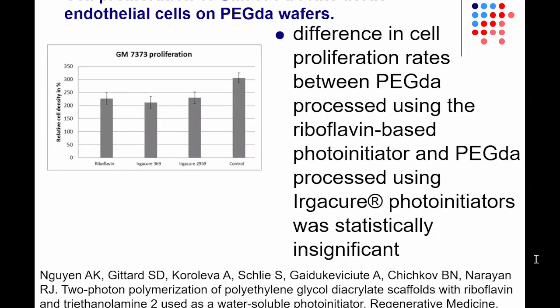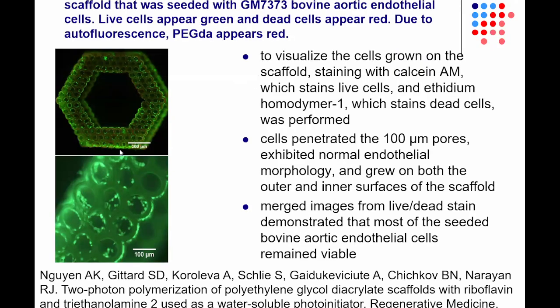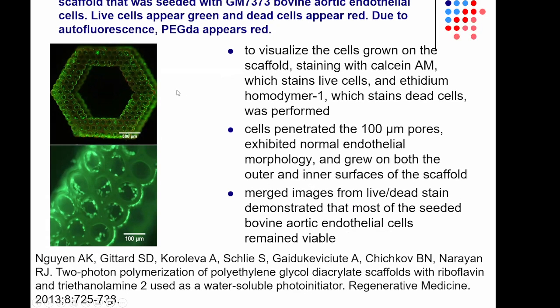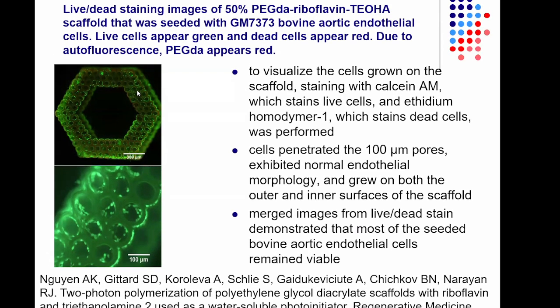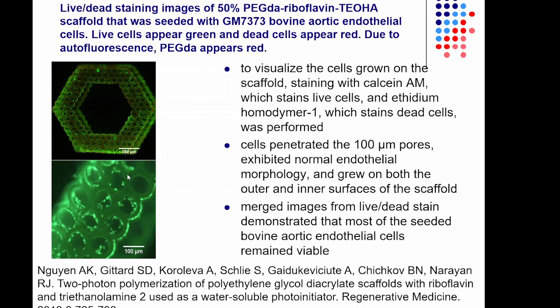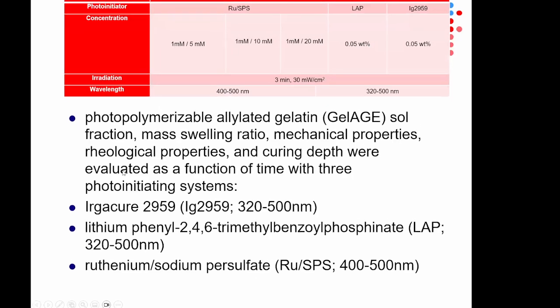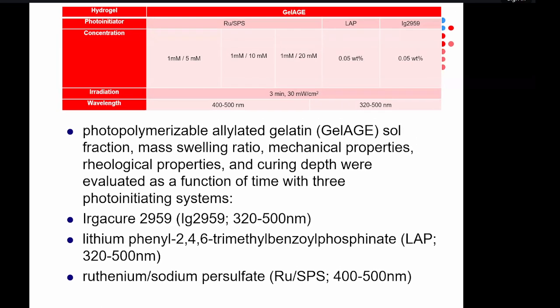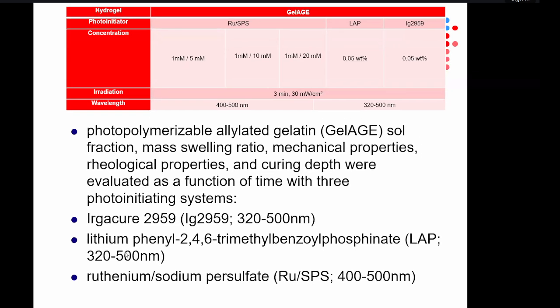These are bovine aortic endothelial cells. Good amounts of cell proliferation of bovine aortic endothelial cells on all of these scaffolds, including the one made with the riboflavin-based photoinitiator. And then if you look at the structure, you have a high number of living cells, low number of dead cells, in the polymerized scaffold. More recently, we started looking at allylated gelatin, polymerized in this material with a ruthenium-based photoinitiator.